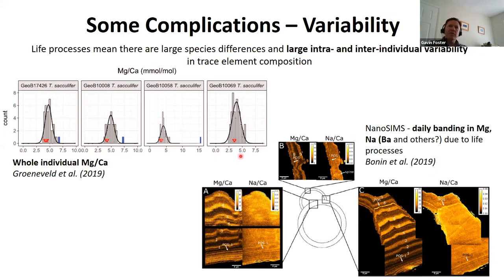Part of that is down to the fact that when we look in detail, there's a lot of variability of magnesium within the shell. This is a NanoSIMS image through the shell wall. I said that they're about half a millimeter in size, and the shells are hollow, and the shell wall is about 20 or 50 microns thick. This is a section through that shell wall, and you can see these bands of high and low magnesium. The bands of high magnesium can be up to about 50 millimoles per mole.